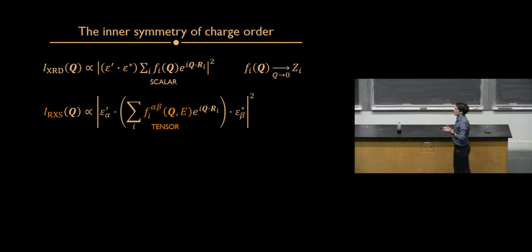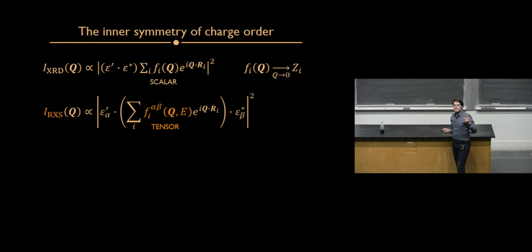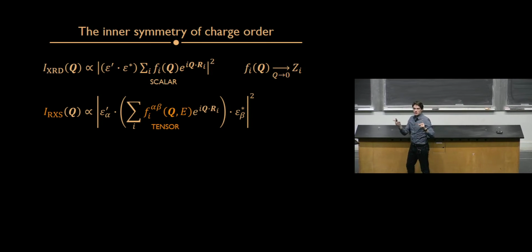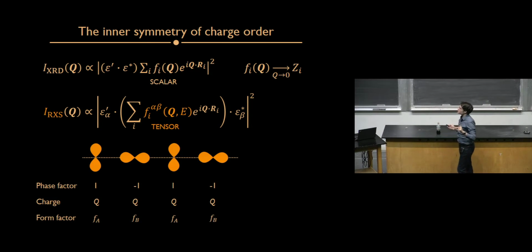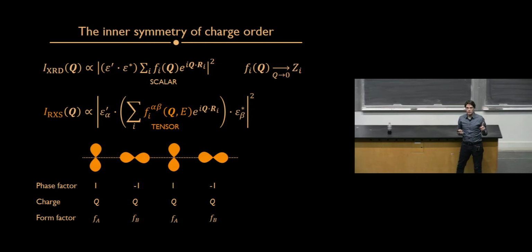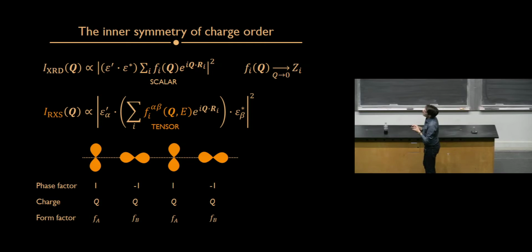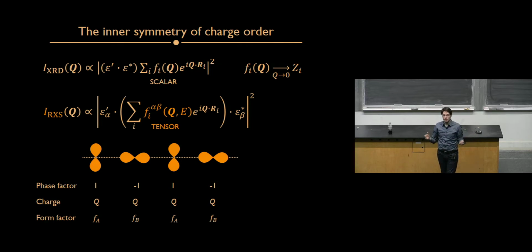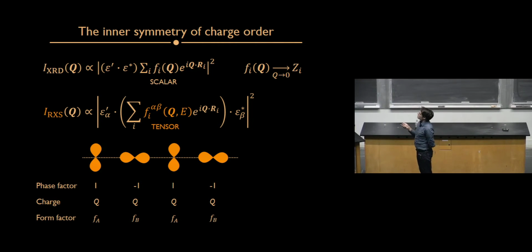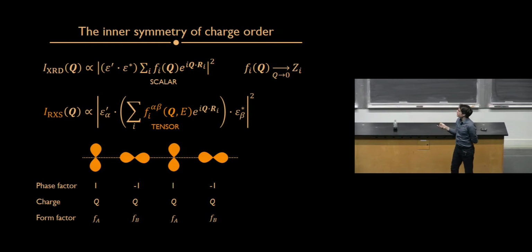Before I discuss that, I want to make one important point, that if you have orbital patterns where the charge is not changing, but the direction of your orbitals is changing as a function of your lattice, then you cannot measure them with diffraction, but you can measure them with resonant scattering. And the reason is that diffraction and scattering have two different quantum mechanical cross-sections. What diffraction measures is something which is proportional to a quantity, which is technically called a form factor, but in the case of diffraction, this is proportional to the Fourier transform of the total charge at a given atomic site. Okay, so just remember this.